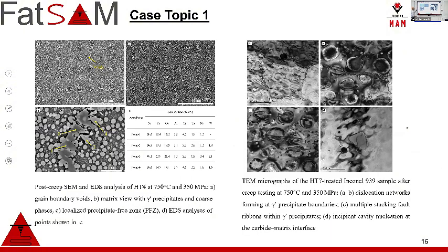Anyway, let's finish. We did some TEM characterization just to see what we can see. This was interesting because, as we know, in fracture mechanisms in creep, we can see everything: all the mechanisms, grain boundary sliding, vacancy replacement, grain boundary migration, element segregation, as well as dislocation motion. In this case, we saw dislocation glide in dislocation networks. In the newly nucleated grain boundaries, we see some multiple stacking fault ribbons and cavity nucleation.